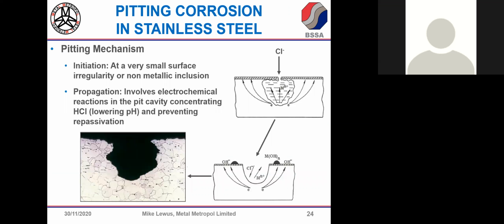So let's demystify some of these mechanisms. Pitting, and why it's quite prevalent in a marine environment, even on something like 316 in atmosphere. I've bestowed the virtues of this passive layer, this chromium oxide layer. Unfortunately, one of the Achilles heels, if you like, of any passive layer metal, and the same goes with aluminium alloys,